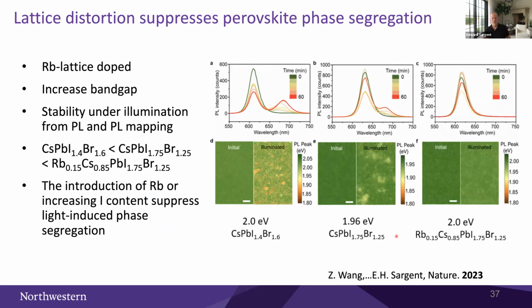Another theme for us has been to pursue triple junction devices. This is a report that I spoke about last year from Dr. Zaiwei Wang and his colleagues, focused on introducing rubidium in order to maintain stability under illumination while increasing the band gap. And in particular, the introduction of the rubidium contributed to reducing the light-induced phase segregation, something we were able to follow by looking at the tail that emerges in reference compositions, but that is avoided when we work with the more stable composition contributed by the rubidium.